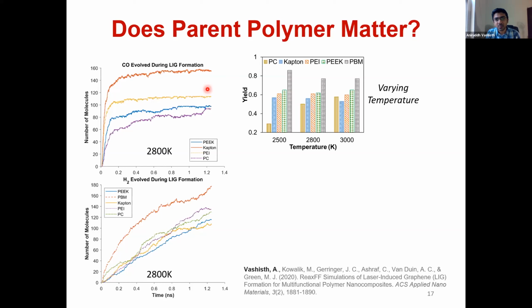Coming back to the parent polymer, we also looked at what is the yield for different polymers. So we looked at a bunch of different parameters. For example, when you have to make LIG from a polymer, you look at what is the input power that you want to use, how fast you want your laser to move. Similarly, in our simulations, we looked at what were the different ramp rates, what is the pressure, environmental condition, and target temperatures that we wanted to use. So if you look here at different polymers, you can see that for PC, the yield actually increases at higher temperatures. But if you look at PBM, the yield kind of plateaus out at around 2800 Kelvin. So that's a very interesting observation: you require higher powers to get higher yield for polycarbonate as compared to PBM.